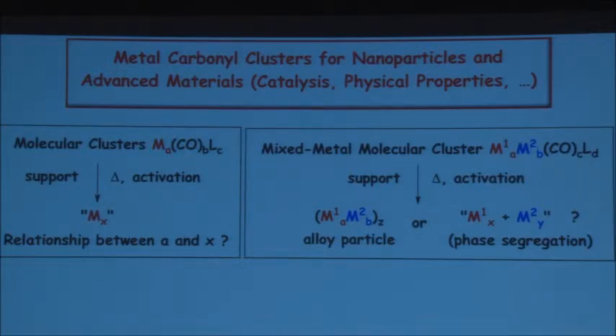What is the size of the metal core? Is it the same as the nuclearity of the precursor? I've taken here A and X because we don't know whether the particle will remain very small or coalesce into larger particles. More importantly, we have a bunch of mixed metal precursors available, where the two metals here are different, chemically speaking. So if you activate them after deposition on support, the question is, are we going to generate very small alloy particles, or are we going to observe phase segregation, formation of particles M1 next to particles M2?